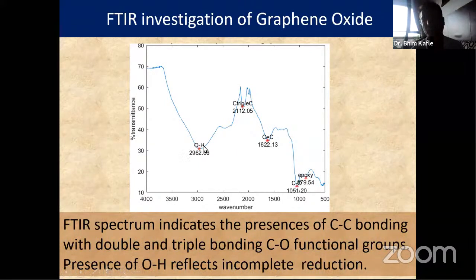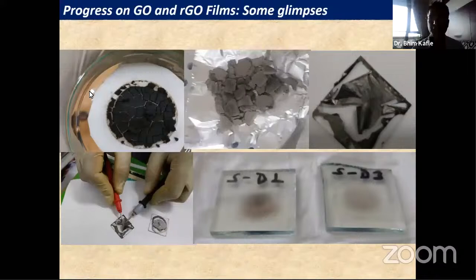Also, it contains, of course, some water. As we did IR spectroscopy of dry powder, it still shows some portion of the water molecule. This is the initially produced graphene oxide. It looks mostly like graphite oxide, and we prepared a film, but after preparing the initial effort, it came out. You can see it has very low heat resistance, and it peeled up.